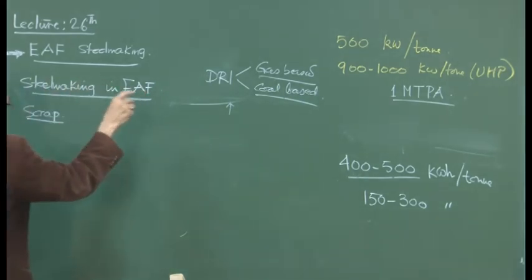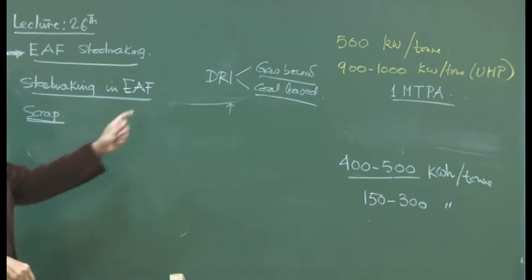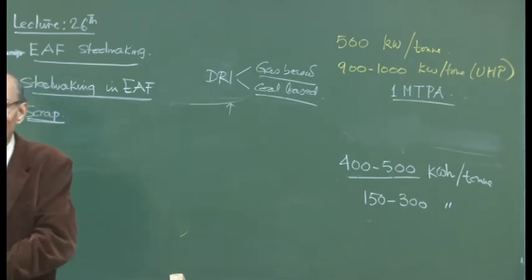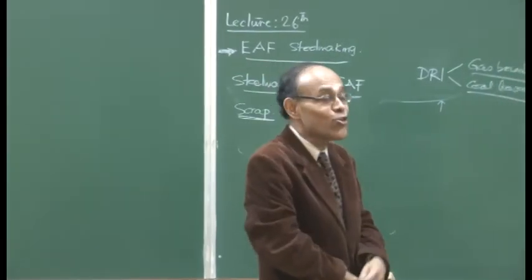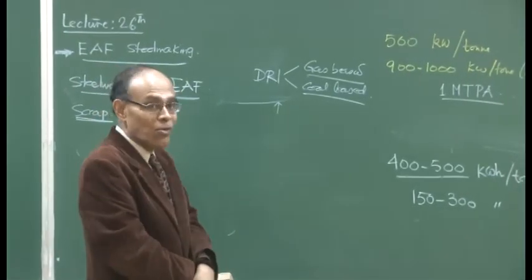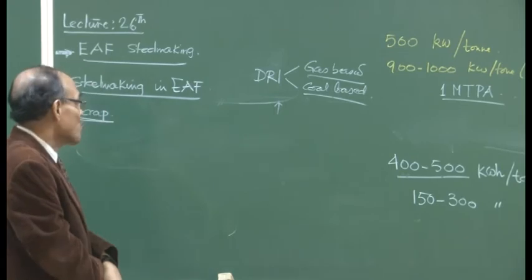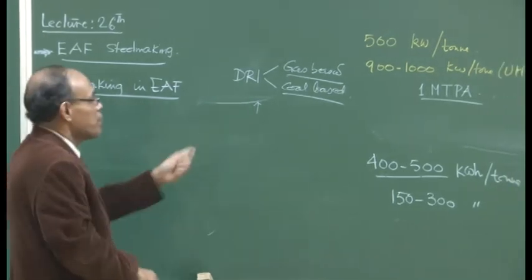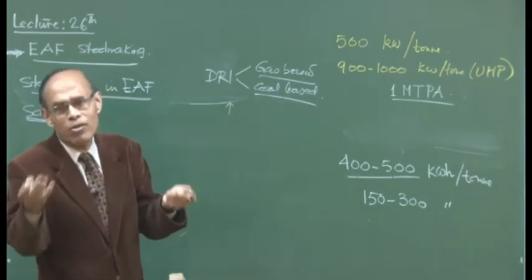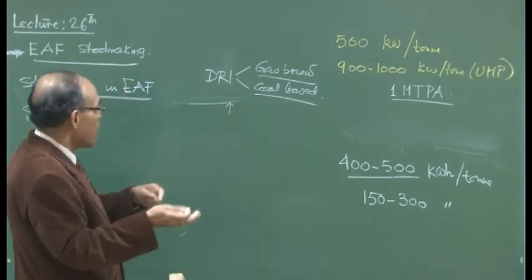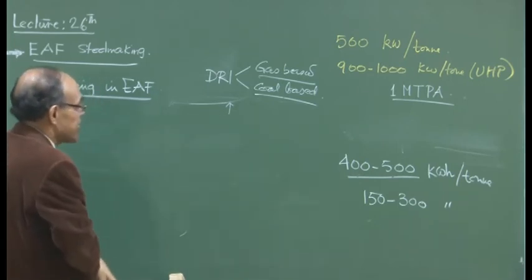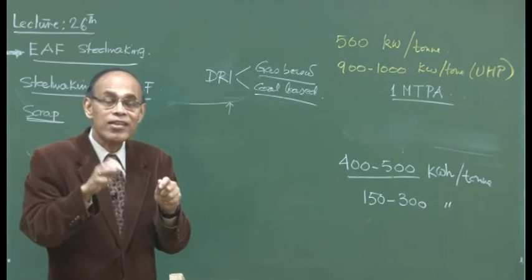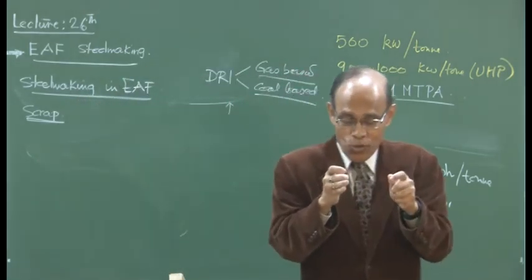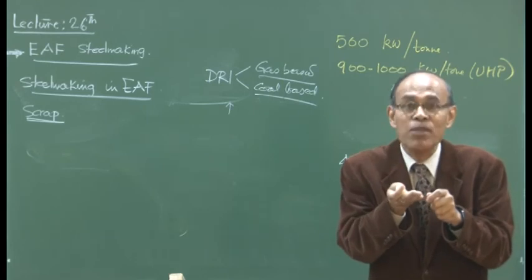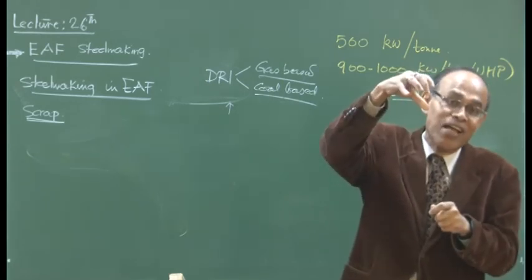So, other than DRI you are going to use scrap, and of course DRI will contain those things which are there in the ore, like some alumina, some silica, and these are not going to be reduced because we do not have any reducing environment here. So, whatever oxides are going to be there, you have Fe is there, FeO is there. If FeO is there, since there is carbon, some amount of reduction, some amount of FeO can go to the slag itself. So, the moment you add DRI, you must understand DRI is a cheap material. Okay. So, if the FeO from the DRI goes to the slag, then that means the slag has now a high potential of FeO.